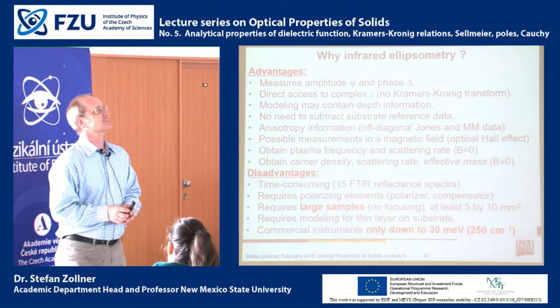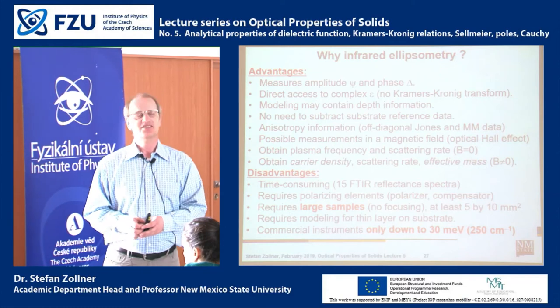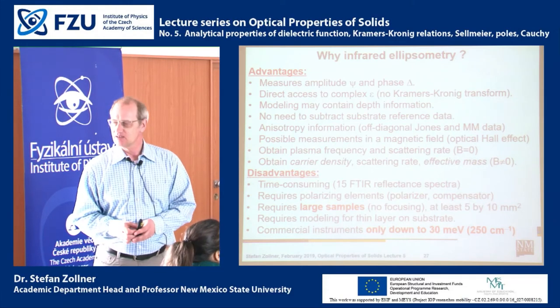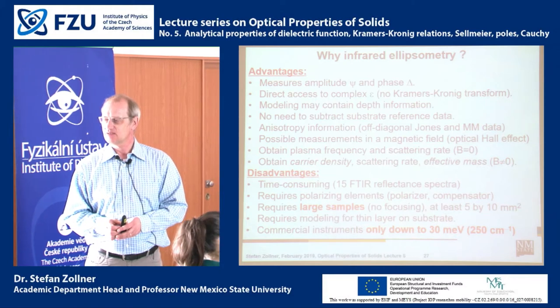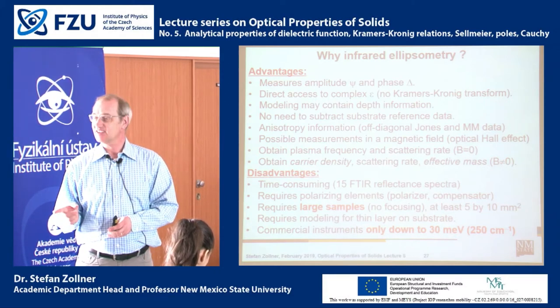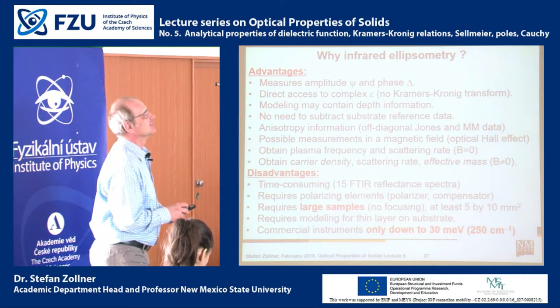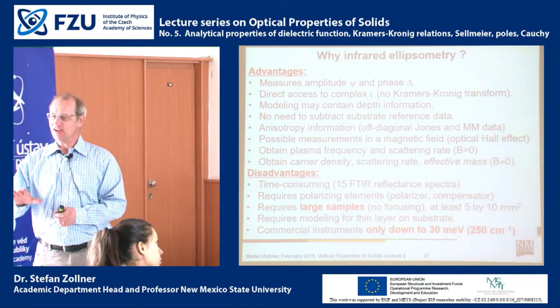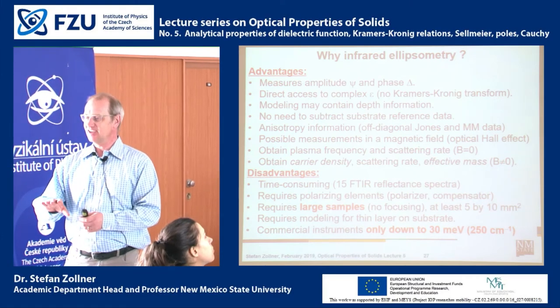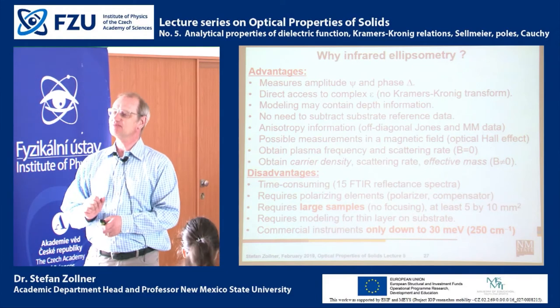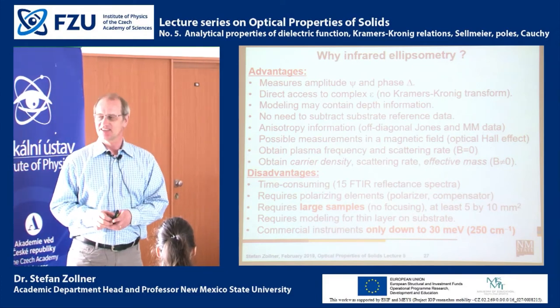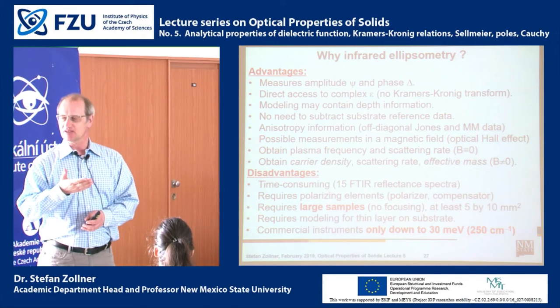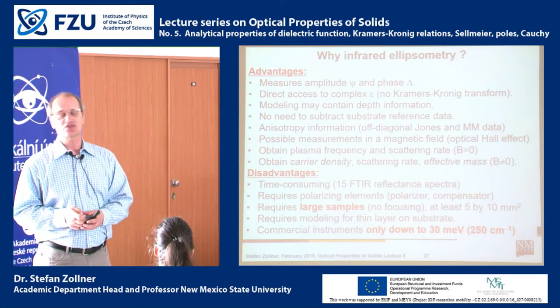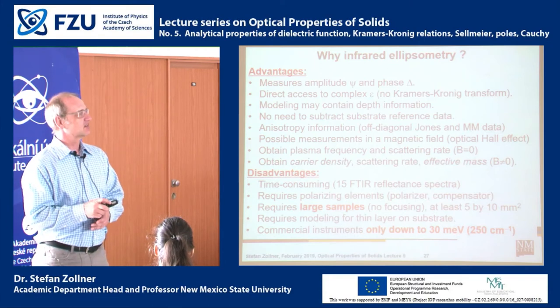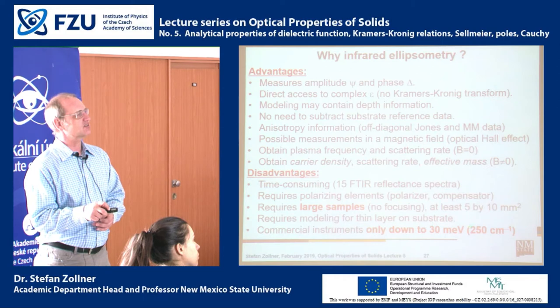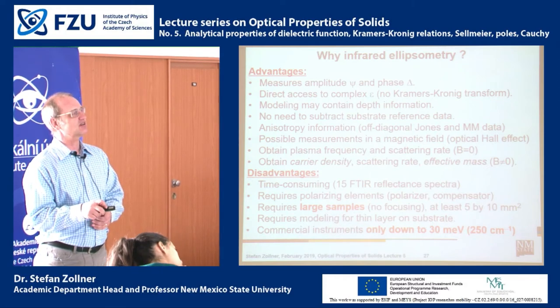Well, my point was if you change the substrate and the reference, you can lose the phase, because you need to put them at the same place exactly. No? That I don't understand. You can cover half the substrate during deposition, and then you have the reference substrate and the film, provided the deposition really did nothing. But sometimes just heating the substrate during deposition may change the surface, so you have to be sensitive to that.